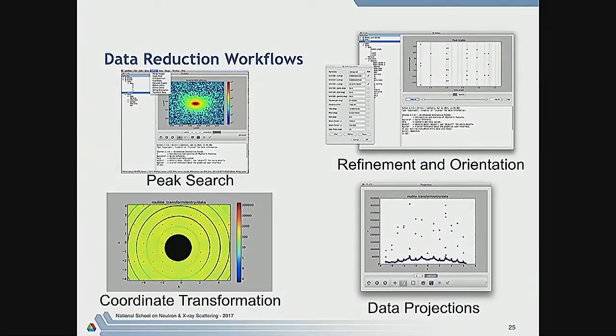Nevertheless, we have over years developed our own workflow, which mirrors what many other groups do as well. We first have to determine all the Bragg peak positions, which allow us to orient the crystal. So here are all the Bragg peaks, and this is 2 theta, and this is azimuthal angle. You can see they all line up on these 2 theta lines. That allows us to determine an orientation matrix, which is the orientation of the crystal in the beam. Here again are all the Bragg peaks.